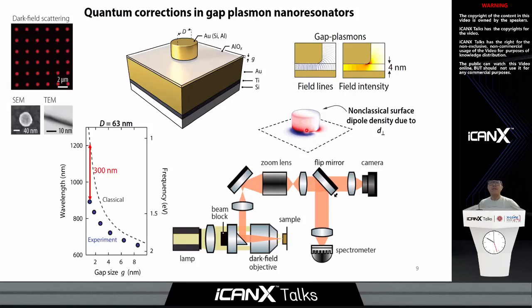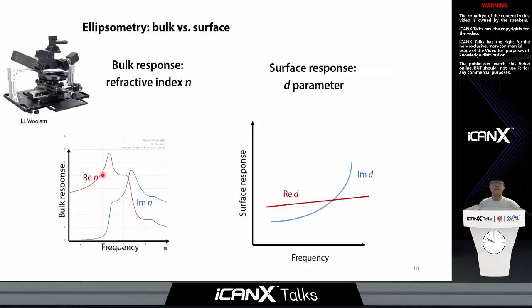We built a tabletop dark field microscope with tunable magnification, and we probed the fundamental dipolar resonance of the structure. We find that there is as large as a 300 nanometer wavelength shift for the smallest gap, around 1 nanometer. This gives us a chance to do an ellipsometry for a surface. The analogy is as follows. We can do a bulk response characterization by measuring the real part and imaginary part of a bulk material using ellipsometry. So what we want to do here is surface ellipsometry, by measuring the real part and imaginary part of the d parameter as a function of frequency.